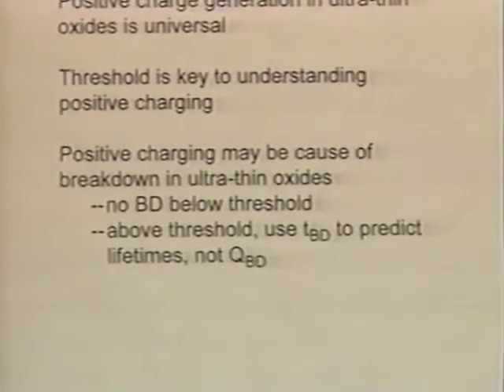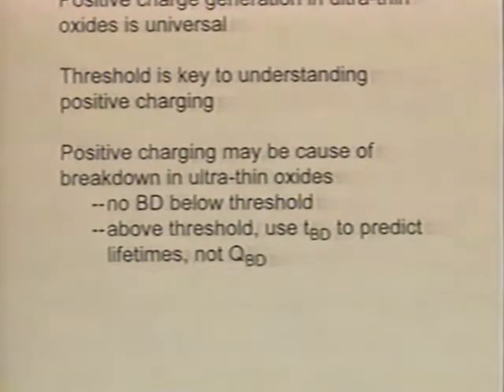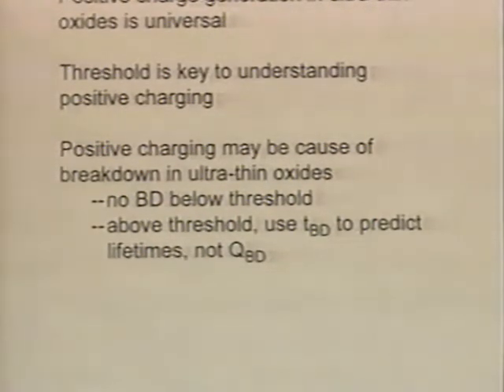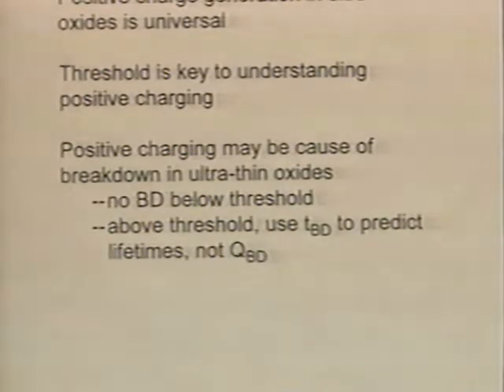Above the threshold, one has to use just time evolution to predict lifetimes. If you're going to use an equation for an engineering approach, you'd need some exponential of the voltage, because there's voltage dependence, some exponential of the temperature, because there's temperature dependence, and then some just time evolution effect. It's not QBD. It's no longer even something that you want to talk about. That's what I claim. And time will bear that claim out. I thank you very much for your attention, and I'll take all questions.